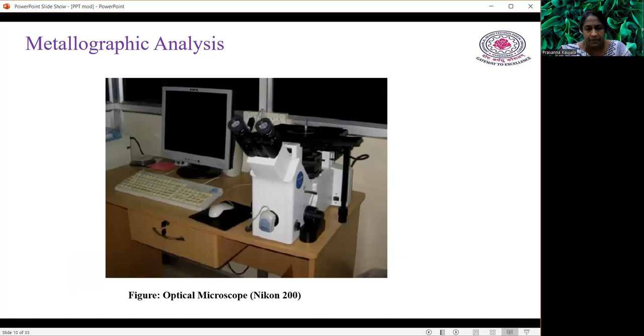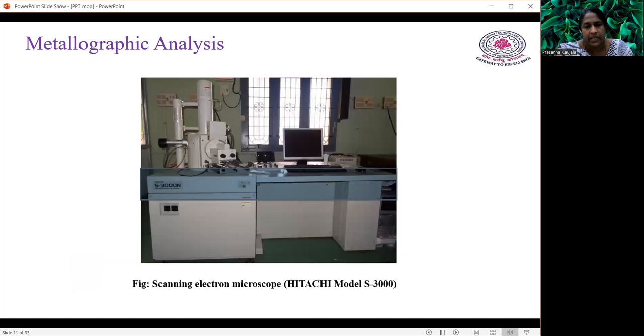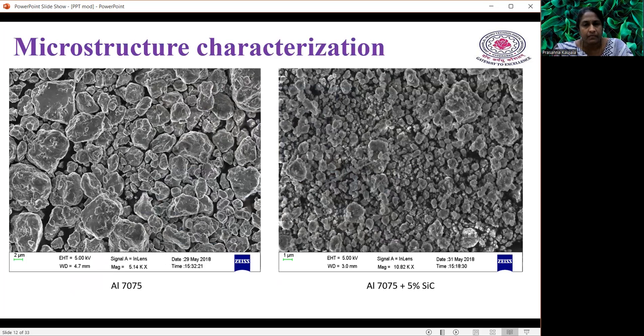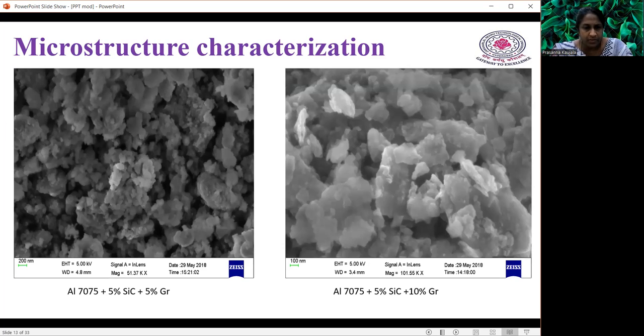So here we are using the optical microscope, OM, for metallographic analysis. And then we again use the scanning electron microscope to find out the microstructure levels, so it can be characterized clearly. Here you can see AL7075 as the base metal. You can see the microstructure, and if 5% silicon carbide is added, we can see the density and how the grain size is varying. Here we have also taken 5% graphite, and the second figure shows 10% graphite. You can see the grain structure difference.